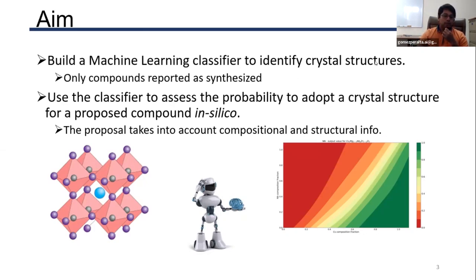In order to probe new chemical compounds with the perovskite structure, we built a machine learning classifier to identify crystal structures. This machine learning classifier was built using compounds reported as synthesized, taken from the Crystallography Open Database. After training the classifier, we used it to assess the probability of proposed compounds adopting a crystal structure, more concretely, the perovskite structure in the cubic symmetry, with the characteristic vertex-shared octahedral framework.